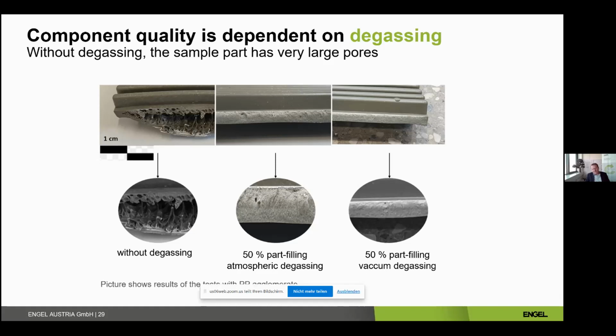And then we have a particular filling of the screw. So we reduce the filling of the screw, and due to the reduced filling, we have a certain free area, and then we just let the gases out to an opening in the barrel. So just via the opening, we got a proper venting, relieving the moisture. And the next step was adding a vacuum pump, which is commonly used in the recycling technology. So adding a venting port on the injection screw in order to remove the moisture content with a vacuum pump. And this also gave a very good result.